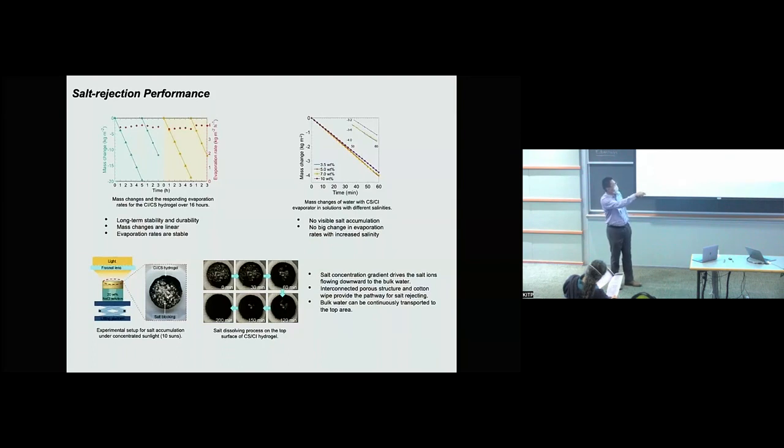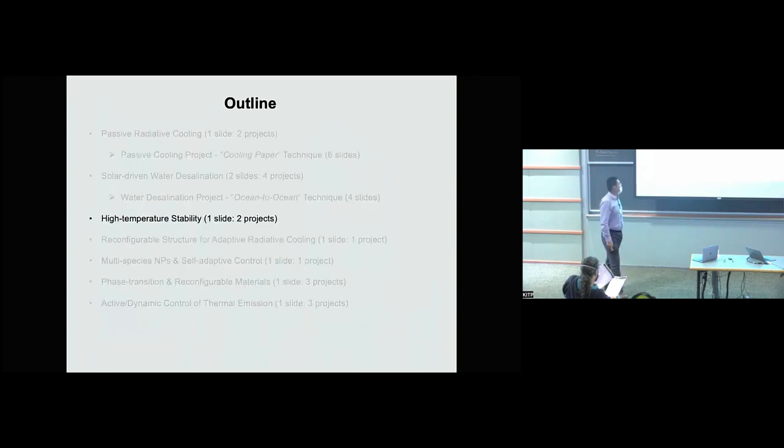This is what we demonstrated: within about 3 hours, all of the salt can be easily dissolved back into the bulk water. We also tested the water desalination rate for different salinities, from 2.5 up to 10. It shows a really nice linear change of mass, and also maintains a really high solar driven desalination rate. For the next few slides, I'm just going to go through really quickly.